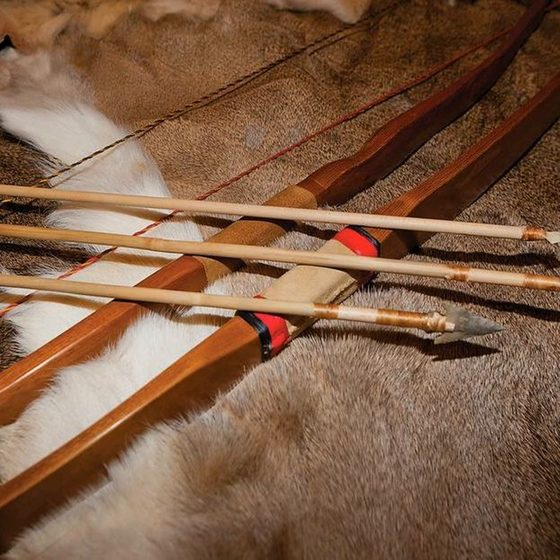Now, there's going to be a balance in there. If you were to go too high in the MOE, really, really stiff, that's where the brittleness starts to come in. This piece is so stiff that if you try to put bending on it, it's going to fracture. You'll find this in the case of hard maple. Hard maple has a very, very high MOE, but in comparison, it has a somewhat lower MOR, bending strength.